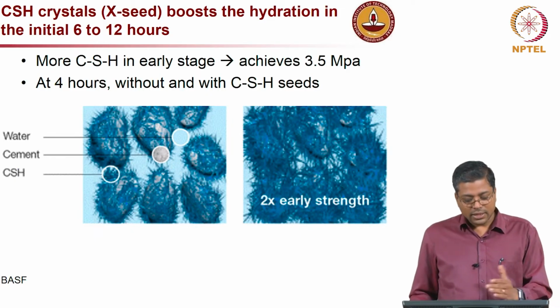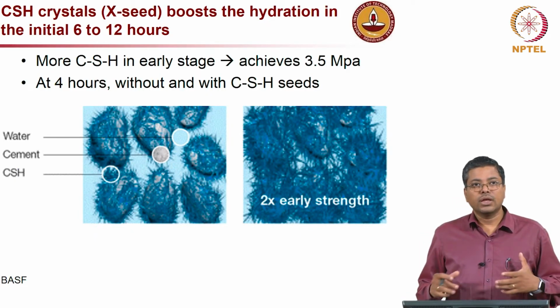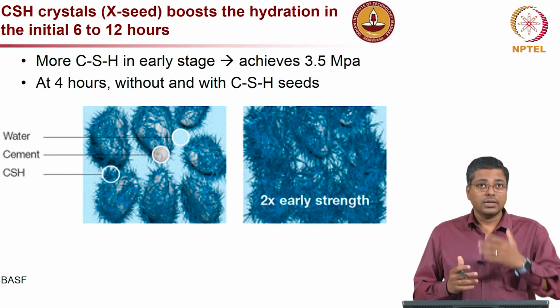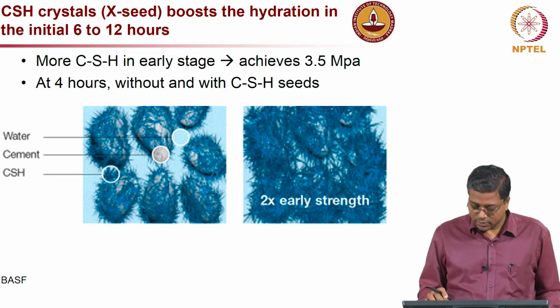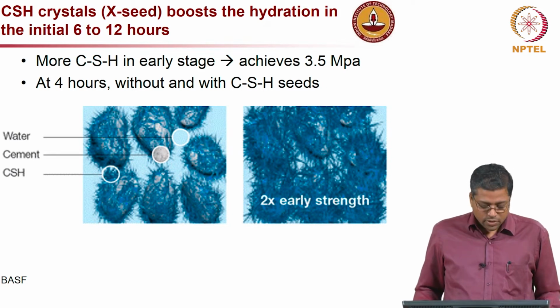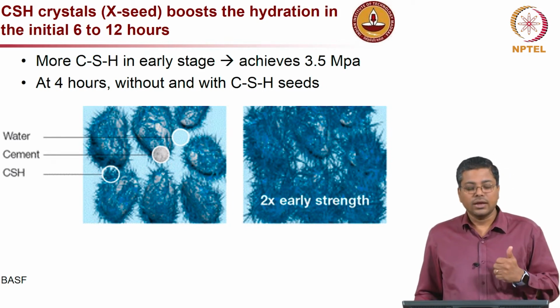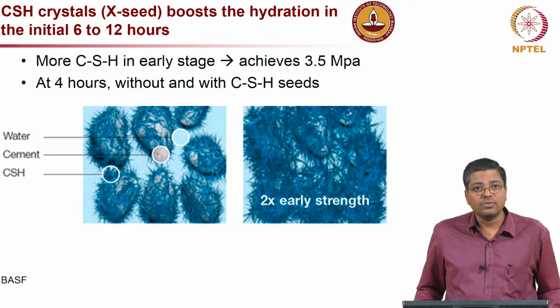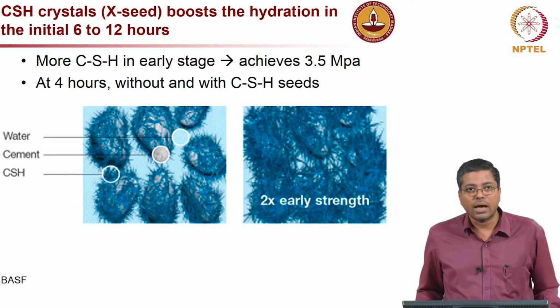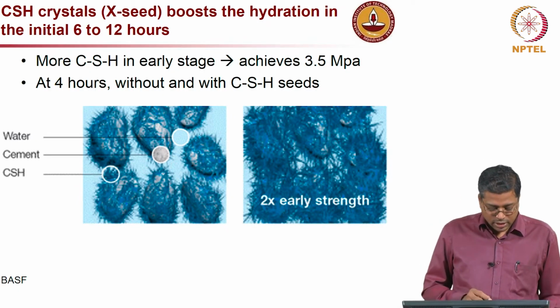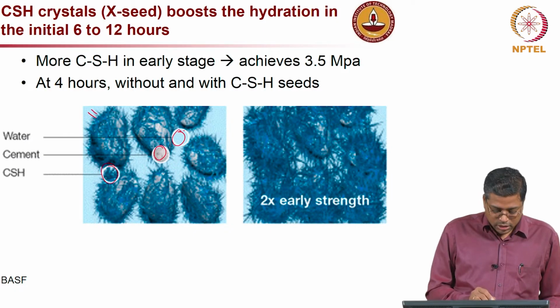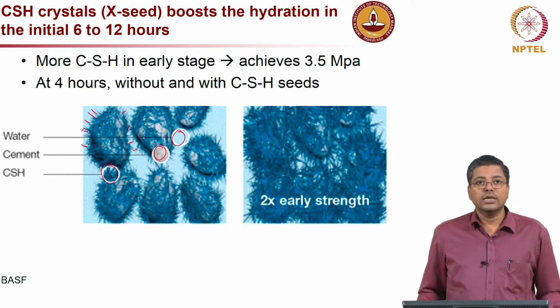Now, there is another technology where the admixtures contain seeds, okay, seeds of CSH, which function like a nucleation point for further reaction to happen and help in setting. What you see here is the CSH seeds, then the cement grain, and then the water, and these are also the CSH and ettringite needles. You will see the needle shaped structure.